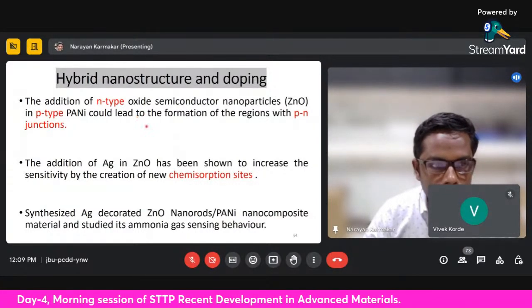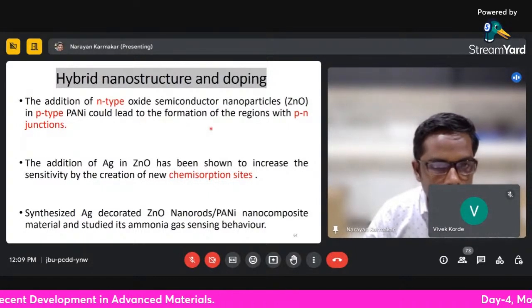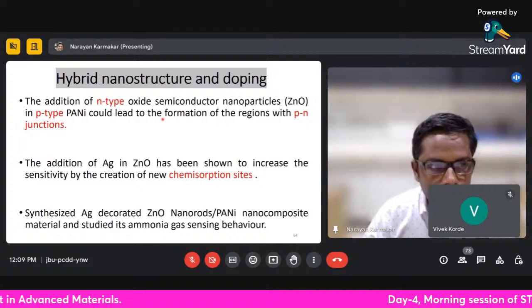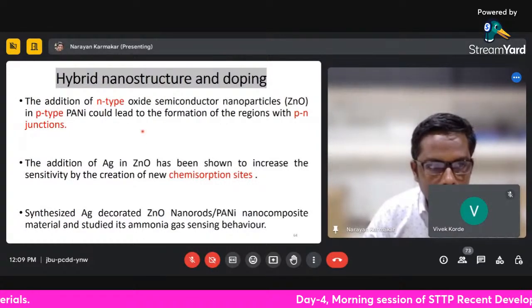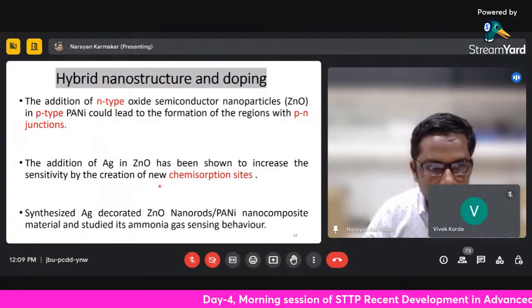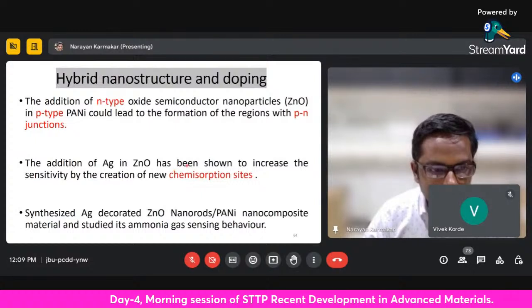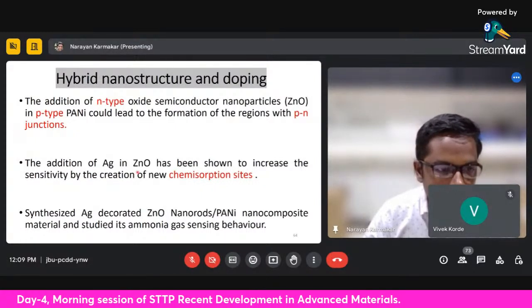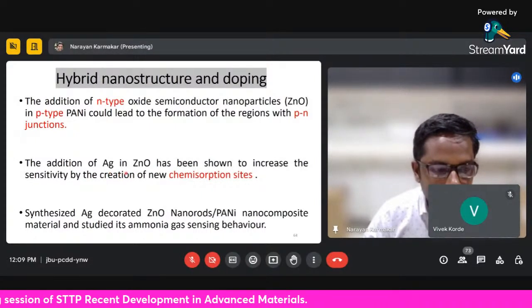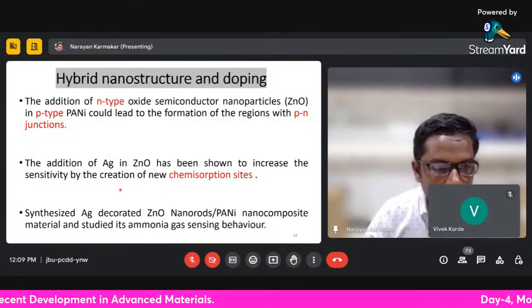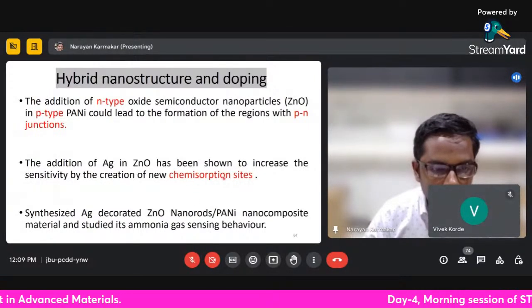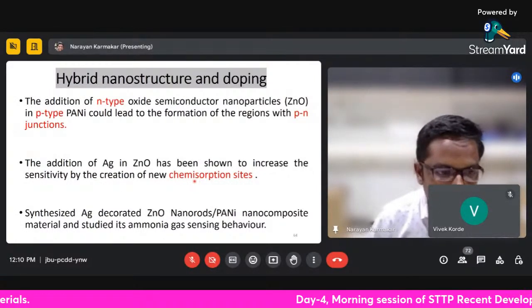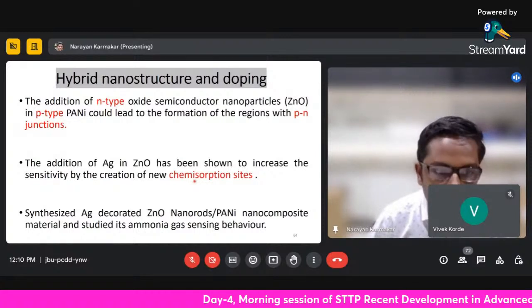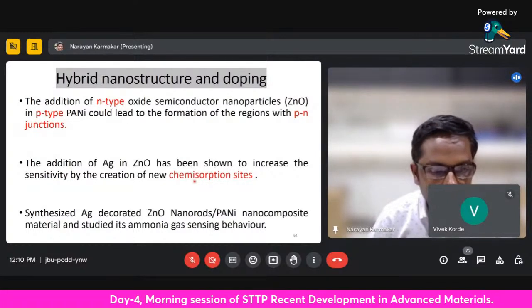So what exactly is this? We have studied the energy levels of this zinc oxide and the Ag. This will result in the PN junction formation, and the addition of silver in the zinc oxide will show an increase in sensitivity because of the new chemisorption site. It is observed that silver plays a very important role in creating a new absorption site.